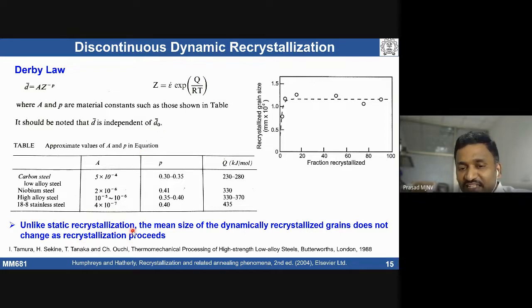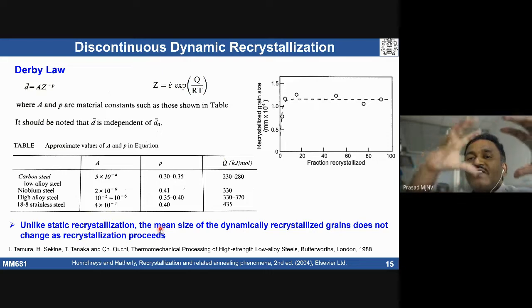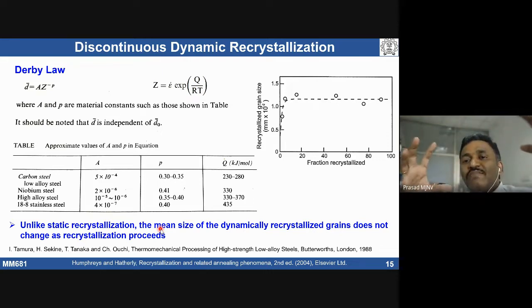Unlike static recrystallization, the mean size of dynamic recrystallization does not change as recrystallization proceeds. In static recrystallization, whatever recrystallized grain is formed is going to grow under static conditions. But under dynamic conditions, we don't see those grains grow because we see a lot of pinning action. During deformation, whatever recrystallized grains are formed, those grains are retained. The size of the grain is going to be almost the same under dynamic recrystallization conditions, unlike a static recrystallization process. So this is about continuous DRX and discontinuous DRX.